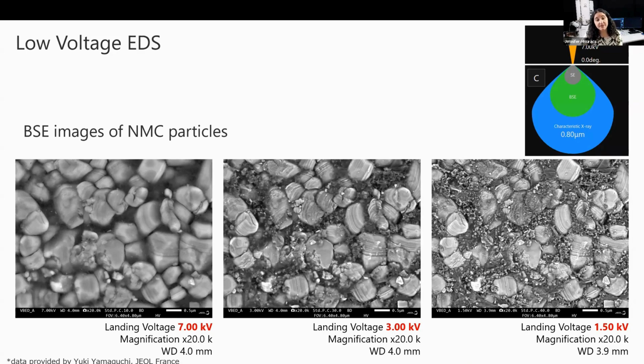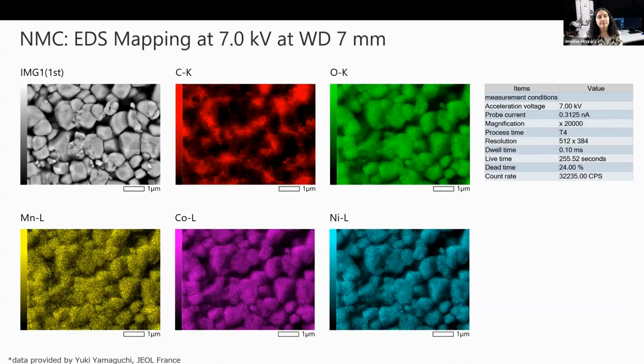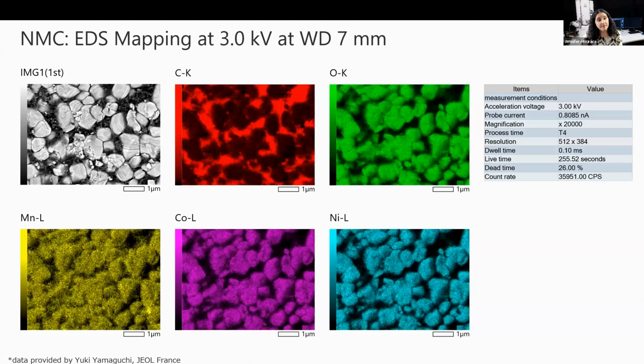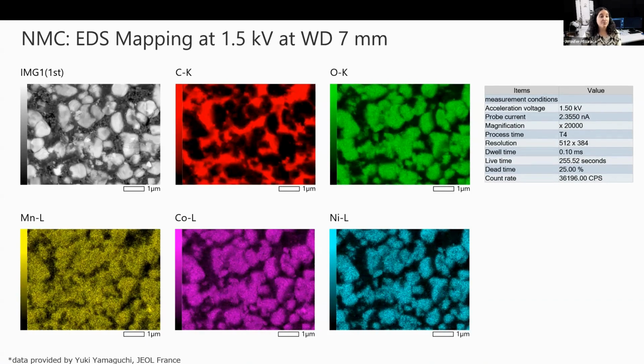The signal depth at 7 kV is shown for a carbon sample in the top right. This signal depth feature is standard on the JEOL SEM software for a quick look at how deep the beam will penetrate into a sample for EDS analysis. This depth will change based on both the kV and the material, which can be selected in the software. Here you can see the corresponding EDS analysis of the NMC at 7 kV, and then at 3 kV, and then at 1.5 kV.